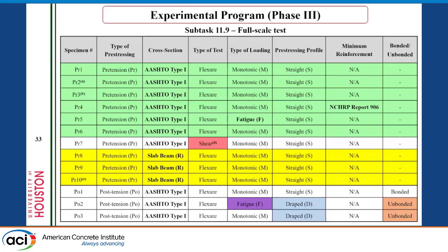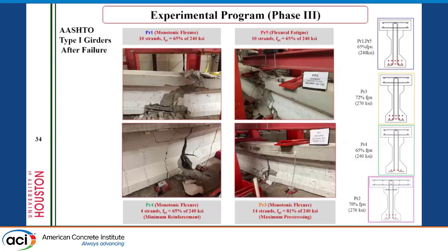We use slab beams where we want to get that balanced condition. We want to get rupture of the strand, concrete crushing. And also we did some post-tensioning to measure the wobble and friction coefficient. So these are some of the results.